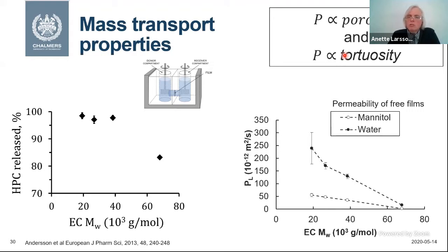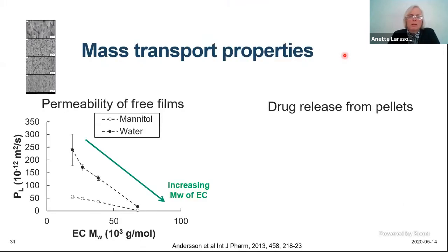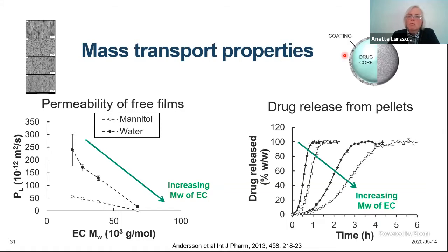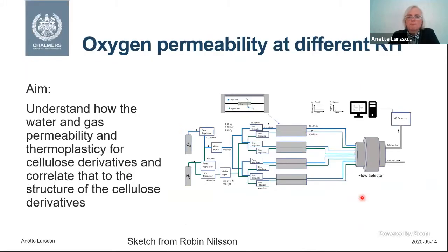Okay, so this was examples for freestanding films. We also tested whether the same was valid for the pellet system, where we have the drug release, how much was leaking out from them. And you can see here that the release takes longer when we increase the molecular weight. And that is also due to the structure of the coating.